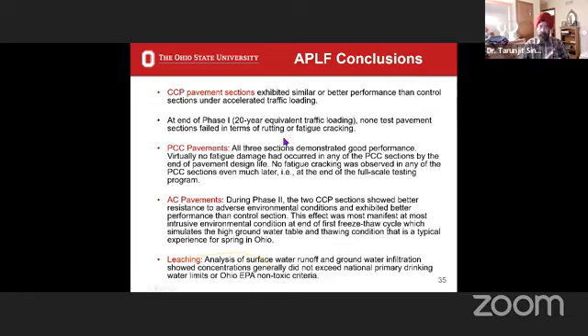Now, it was different in phase two. For the Portland cement concrete pavements, they did not fail even in phase two. There was no fatigue damage in any of them. In fact, our observation is that for the concrete pavements, the control and the CCP section behaved similarly. None was better than the other.